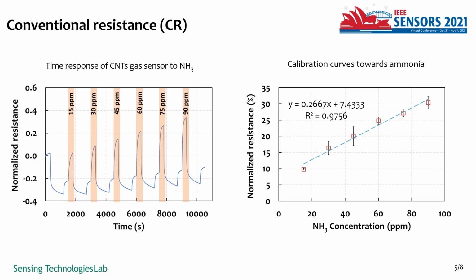So here we have the time response of the carbon nanotube gas sensor to ammonia when conventional resistance was used as the measurement method. And we can see here the normalized resistance versus time. We have these red zones, which are the sensing intervals where the sensor was exposed to ammonia for 5 minutes. And we can see that the concentration was increased from 15 ppm to 90 ppm with a step of 15 ppm. And here we have the calibration curve towards ammonia, the normalized resistance versus ammonia concentration. As we can see, when ammonia concentration was increased, the normalized resistance was also proportionally increased. And we got a sensitivity of 0.266 and a coefficient of determination of 0.97.